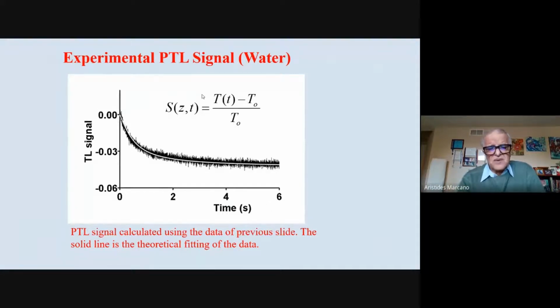And from this same experiment, you can see the evolution. The signal is negative, as expected, because of the negative value of the thermal lensing effect. This is the defocusing lens. You can see the time evolution of your signal, and you can get a very good fitting with the theoretical model. You can see the signal is small, it's 0.03.